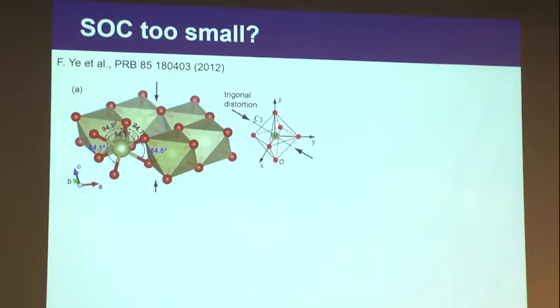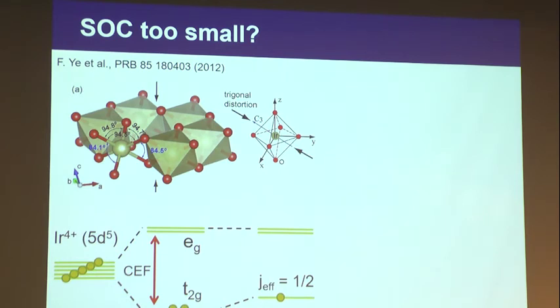It turns out that what's important in talking about energy scale is not necessarily the bare strength of the energy itself. When you compare energy, it is always one energy to another energy, right? So you cannot say spin-orbit coupling is too small or too large unless you compare it to something else. So what is it that we want to compare it to? It turns out that it is the small additional crystal field splitting due to non-ideal geometry of the octahedra. When I showed you this diagram, I assumed a completely octahedral environment. But if you look at the crystal structure of sodium iridium oxide, it is squished from top and bottom. Therefore, the angle between these is larger than 90 degrees, 95 degrees, and the angle sideways is slightly smaller than 90 degrees.